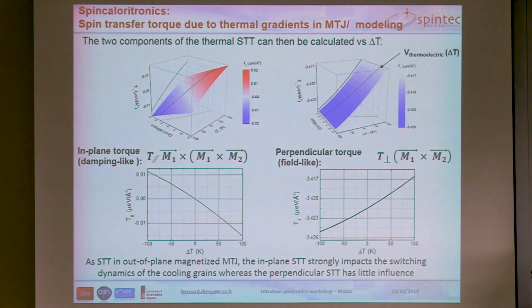Next, we can calculate with the formalism the two components of the spin transfer torque: the in-plane, which has a damping-like form, like the usual spin transfer torque, so this form, which resembles Gilbert damping. And we can calculate the perpendicular torque, which resembles the precessional field-like term. And we know from spin transfer torque in perpendicular magnetic tunnel junction that actually this in-plane torque plays the main role in controlling the switching of the magnetization. This one changes the frequency of the precession during the switching, but does not change the critical condition which determines when the magnetization is switching.